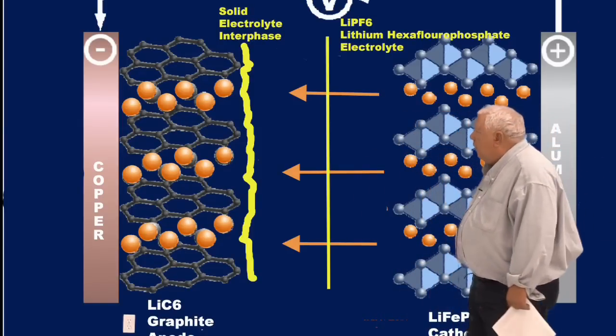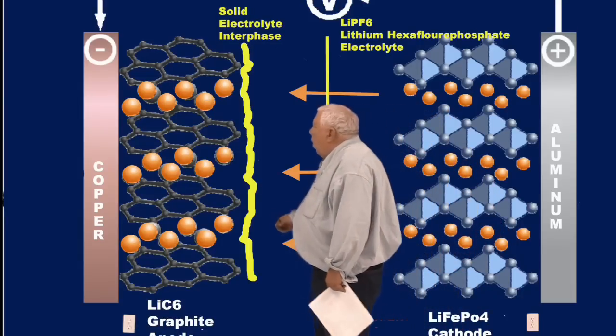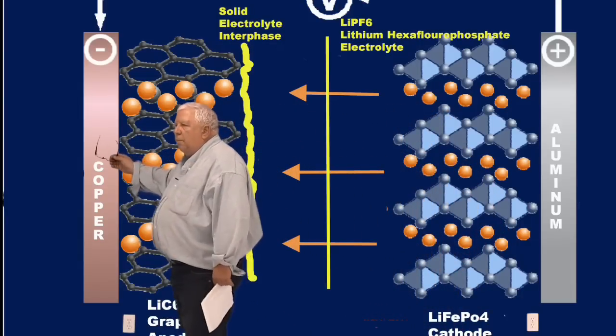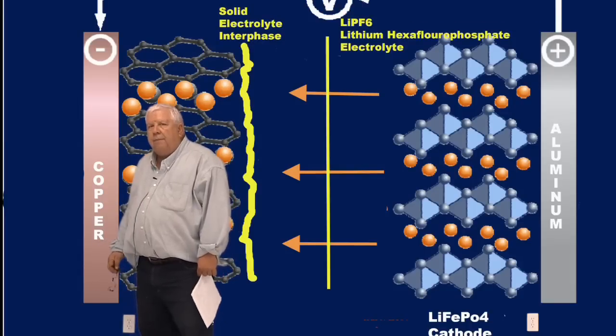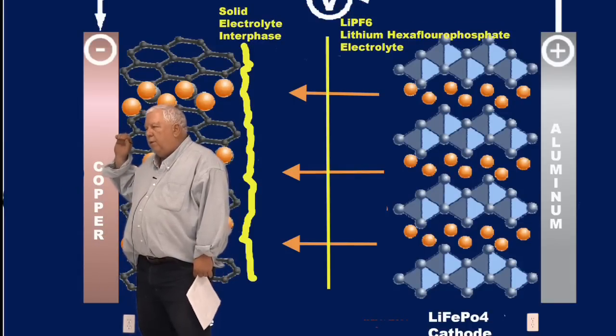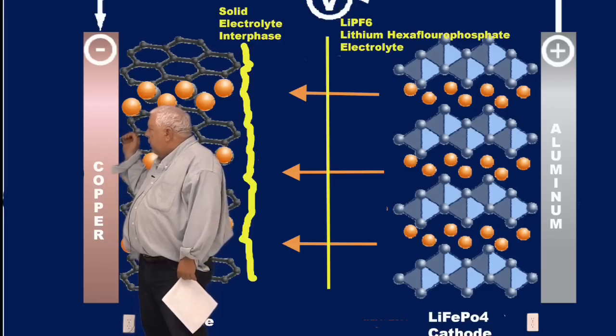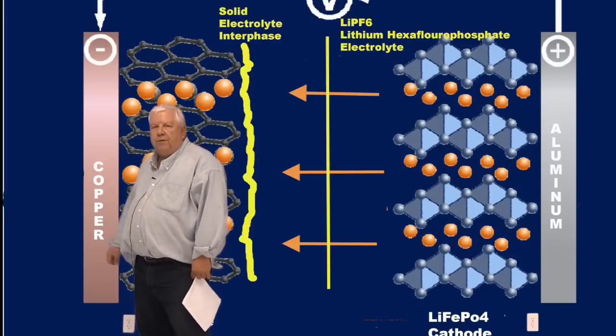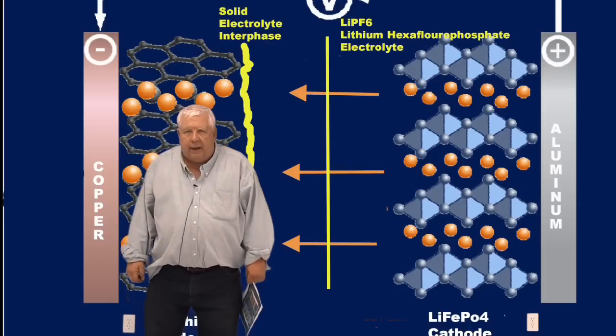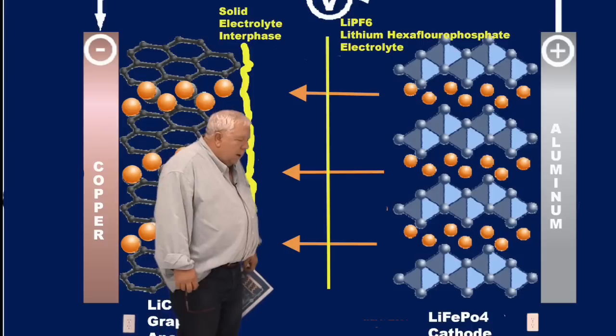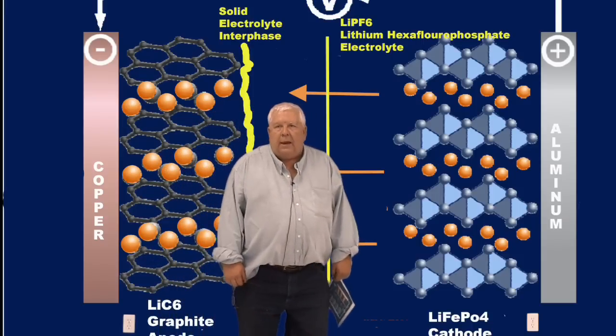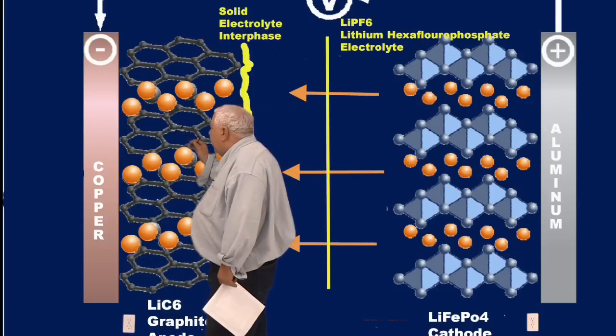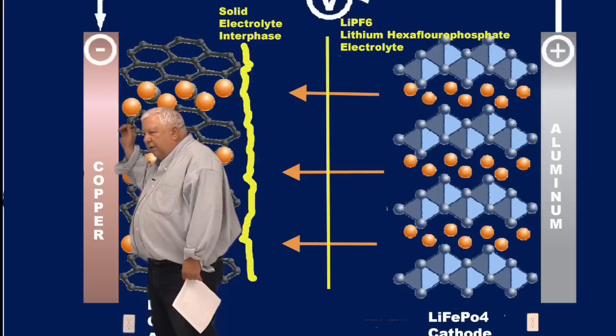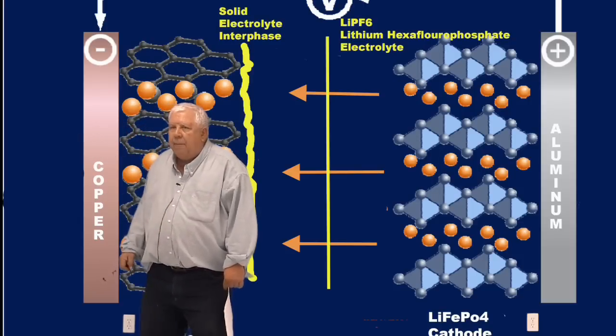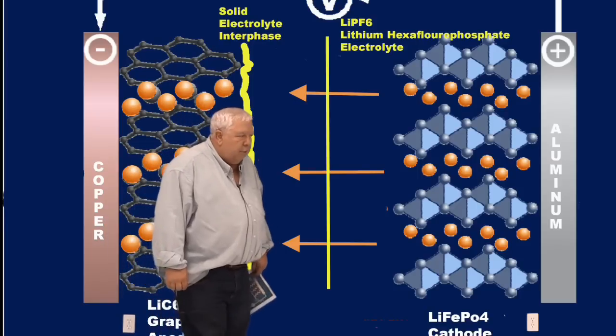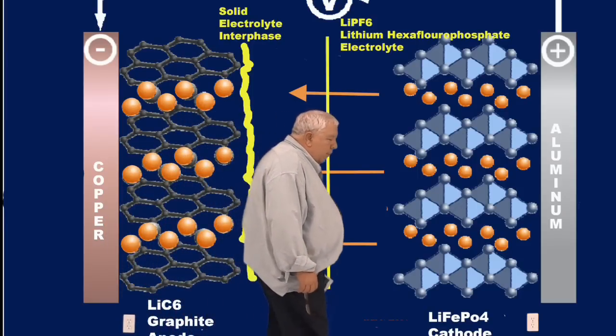If nothing else, the iron plates on our SEI layer, diminishing our capacity substantially. And worse, later, if we discharge the cell and recharge the cell, now we have lithium that's blocked on the surface of the SEI layer by iron plating. And so the lithium plates onto the iron. And as that builds up, it reacts with the SEI layer, with the solvents. And so we have this massive scab growing on our anode and diminishing our capacity.